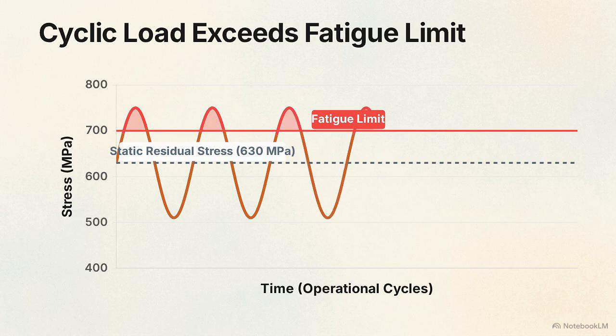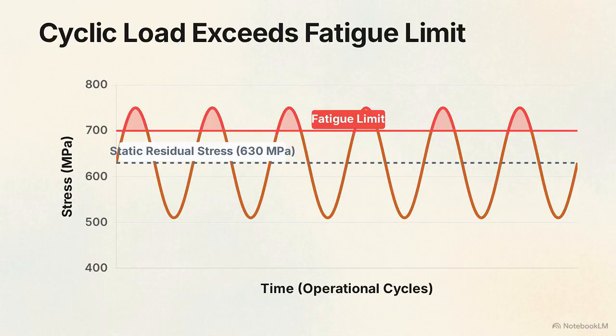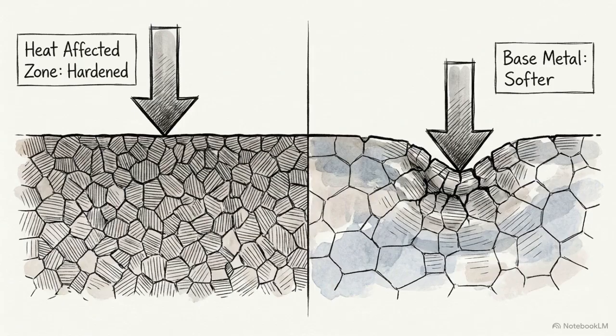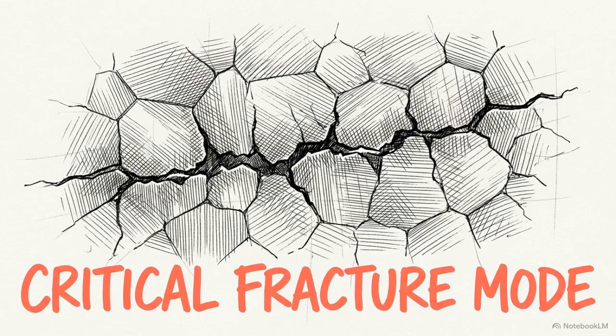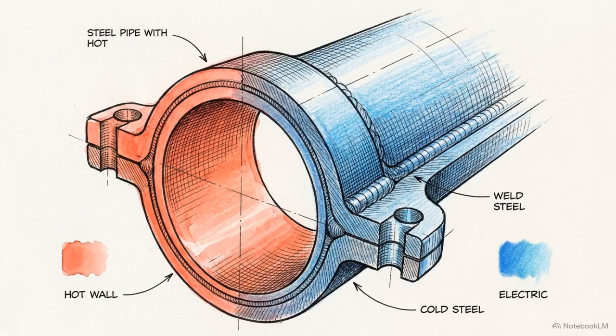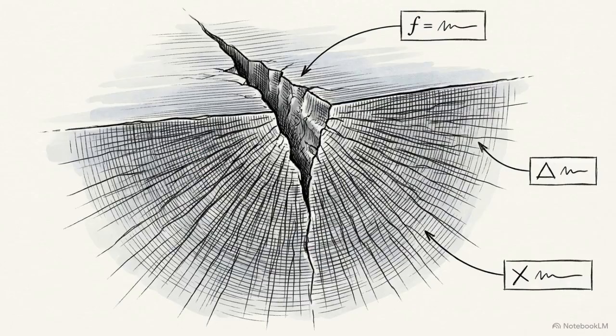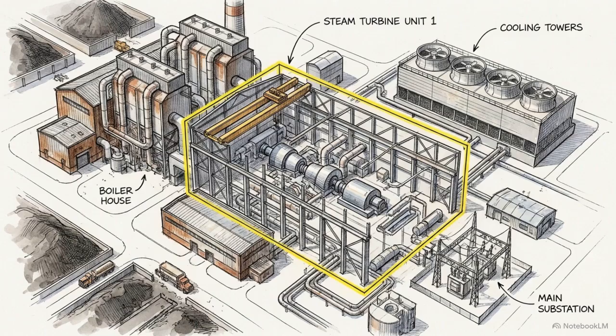This combined load pushes the local stress state beyond the material's structural fatigue limit. While the hardened structure of the heat-affected zone could resist this peak, the softer base metal could not. It was pushed into a destructive low-cycle fatigue regime. The non-symmetric residual stress altered the mean stress ratio inside the joint, creating the conditions for crack initiation in the compliant base material. This forensic analysis carries implications for mechanical design across the power generation sector.